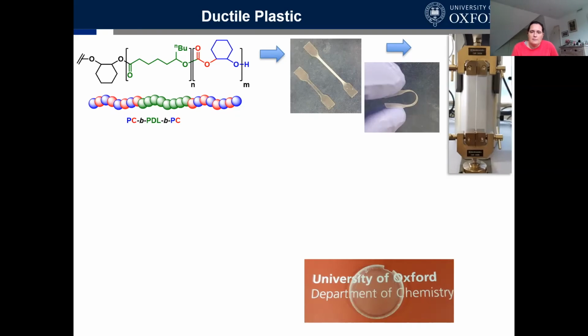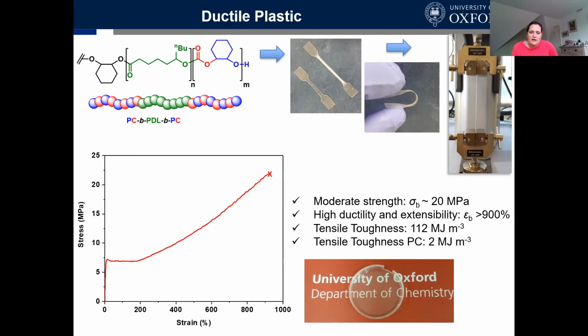And you can then plot the stress against the amount that the material stretches, the change in length of that material. And we can see that it's a typical plastic in that it has a yield point around 7 megapascals, and then it eventually breaks at about 20 megapascals, showing 1000% elongation compared to its original length. So it's got a moderate tensile strength, as I say, about 20 megapascals, certainly well within the regime of something like polythene, has high ductility and extensibility, higher than many plastics we use today, and it has good tensile toughness.